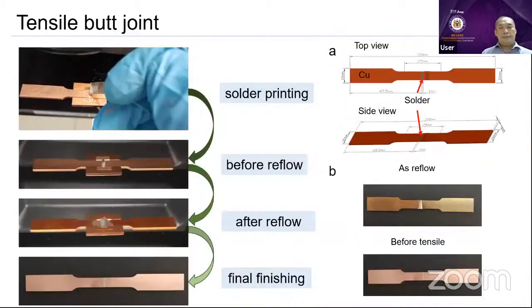Then for the tensile properties, we do a butt joint. We make a very small gap here and put the sample in. If you can see here, we need to put another copper piece here, because we need to make sure it fits that gap. At the end of the day, we can just remove this as one component and have a very nice final finish. We take this one and run the tensile. This one is as-reflowed, and this one is before tensile.